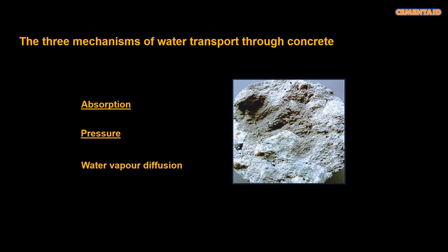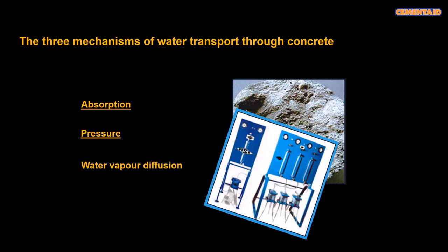If you want to test the pressure permeability of concrete, use a rig something like this, where samples are put into it, subjected to a head of pressure over a given area, and from that they say you calculate the permeability. In fact, you don't, because permeability is a measure of water movement through a fully saturated medium. These samples very rarely get saturated. What you do, you break them open after a period of time and just measure the depth of ingress. And there's a third category here, water vapor diffusion, which is a very, very slow process.